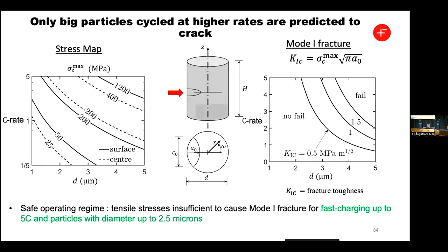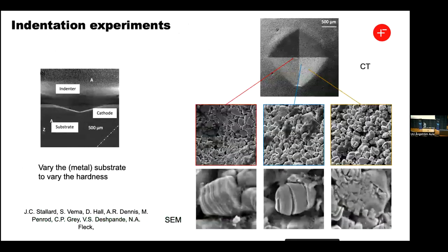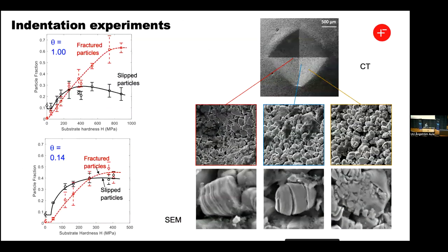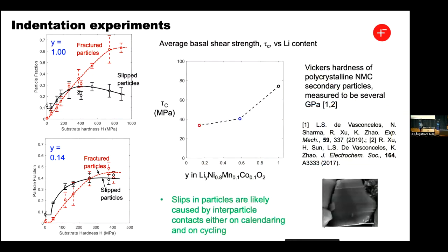So then to think about this further, we looked at some indentation experiments. This is now actual physical measurements, done by Joe Stallard. He comes in with an indenter and compresses an electrode of particles, and you change the substrate and the hardness of the substrate, and depending on the hardness, you can get different mechanical force. You can then look at the images and count how many fractured particles you have and how many particles have slips, not slippage, to be clear. You can then see that you get very different numbers as a function of state of charge. And so what he was able to do was to quantify the force you need to push the particles this way.